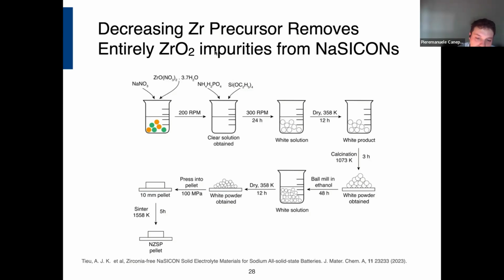And what we are trying to design is a synthesis of Nasicon which is zirconia-free. As you will see in the remainder of the talk, in the last few slides, if you don't take precautions in how you synthesize this material, and here I must admit I'm a little bit out of my depth, you can have monoclinic zirconia as one of the materials that is formed during the synthesis. And having monoclinic zirconia is not detrimental, but of course it changes the morphology of your grain boundary, changes the temperature of sintering, and might have a direct impact on the conductivity.